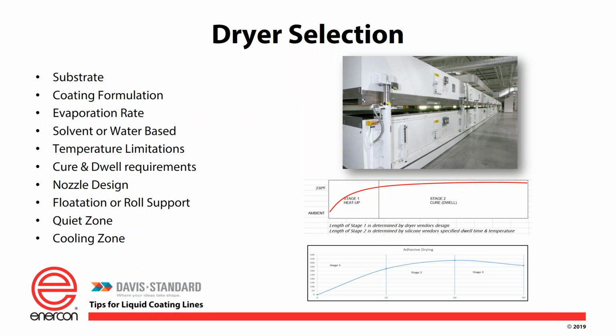Coating formulations, again, I mentioned to you that we want to know what that formulation is, so we can look at how much heat to be applied to the evaporation rate to dry that product, to turn it from a liquid to a gaseous form without disrupting the top layers or other layers. If you dry it too fast, you can actually get a skin formed on the top, and now the liquids underneath can't get out, so they'll start to boil and blister and break through the surface. Something like that, you want to dry more from the bottom on the thicker coating to start with than you do on the top, and maybe even a quiet zone where there is no drying on the top, right?